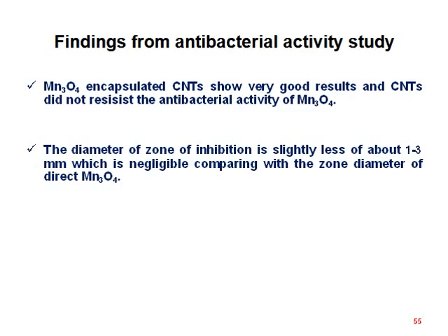Now let's look at the findings from the antibacterial effectivity testing. Manganese oxide encapsulated CNTs show very good results, and CNTs didn't resist the antibacterial effectivity of manganese oxide. The diameter of the zone of inhibition is slightly less, by about 1 to 3 mm, which is negligible compared with the zone diameter of direct manganese oxide. As CNT is a well-established drug delivery agent, and from our antibacterial experiments the effectivity of the drugs is comparatively unchanged, it can be said that CNT can be easily used as a drug delivery agent